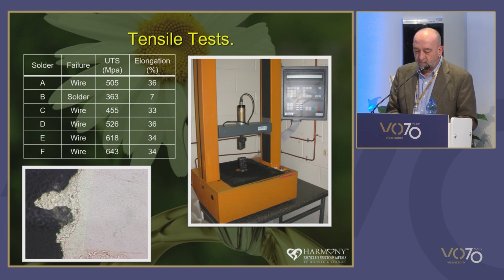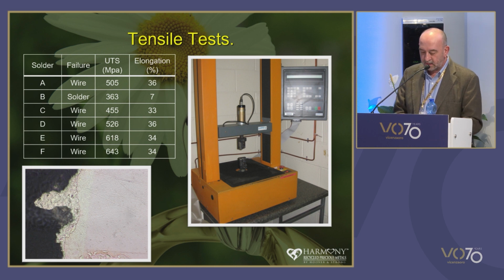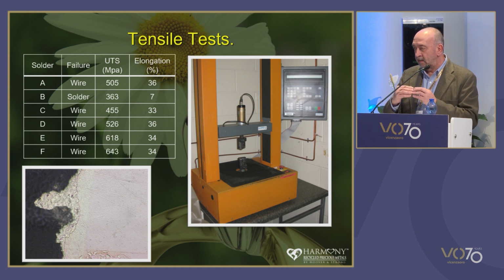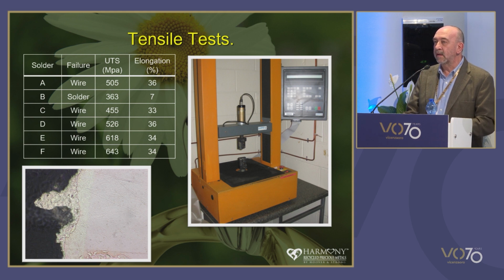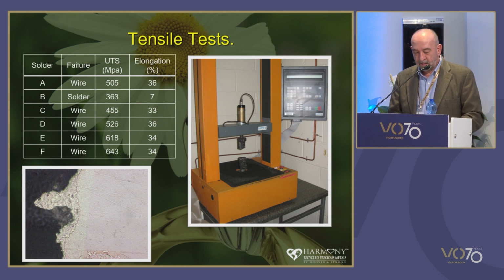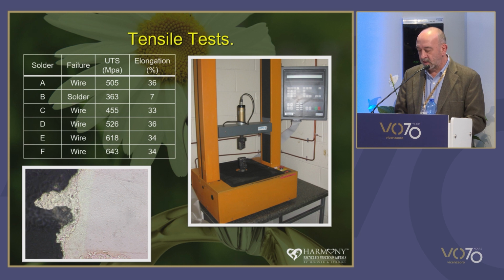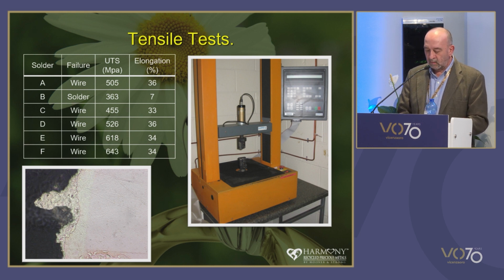So the third test we did was to simulate a ring sizing operation, and this is one of the most common jewellery repairs there is. So sizing is done by either removing a section of a ring shank and soldering the ends together, or inserting a piece of sizing wire into the shank and then soldering this. Either way, it's a typical example of a butt joint. So to do this, we took some test rings that we made from 3 by 1.5 millimeter round wire, and for each soldering test, we prepared 3 samples.